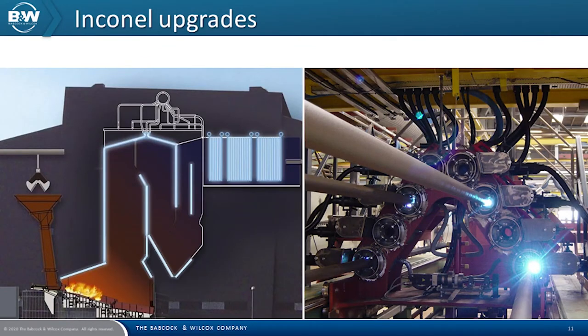Babcock and Wilcox pioneered the use of Inconel as a solution to the lower furnace corrosion problem, as well as other corrosion susceptible areas. As early as 1986, the lower furnace tubes in a refuse-derived fuel-fired boiler in the United States were covered with Inconel weld overlay material. This overlay effectively minimised corrosion, and based on this experience, the industry followed Babcock and Wilcox's lead. Inconel weld overlay was subsequently field applied to the lower furnace areas of a number of operating boilers.